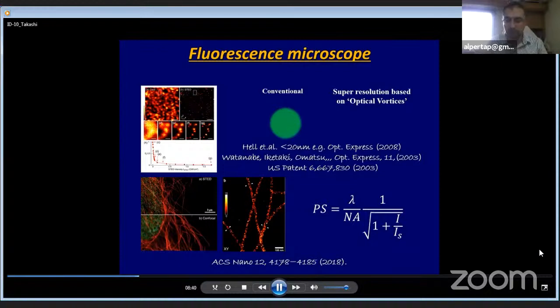How to use such orbital angular momentum light, optical vortex? The most famous application must be the improvement of spatial resolution in the fluorescence microscope. Generally speaking, the spatial resolution of a fluorescence microscope is determined by the pump spot size on the irradiated target. Okay? The pump spot size is typically half a micrometer because of the diffraction effect of the light. Okay? The pumped region radiates a fluorescent signal. The fluorescent signal has some micron scale.